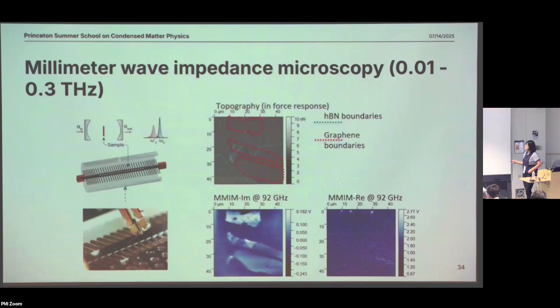So it seems like now we can also do scanning measurements at 92 gigahertz. And this bright region, which means the sample is more conductive, has a good coincidence with the graphene boundaries. You can scan those materials readily here and there, while hBN just doesn't have that response because its conductivity is really small, similar to the background silicon conductivity. And then in the real channel, because graphene is a pretty good conductor, it just doesn't show too much dissipation. So that's as expected.